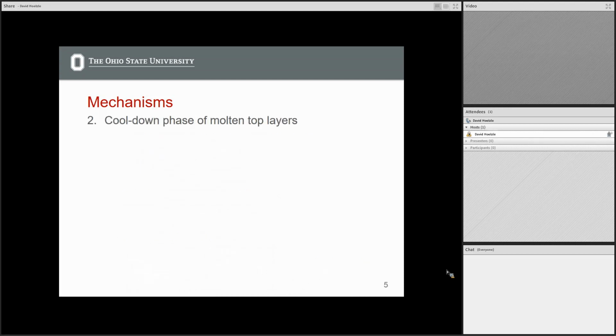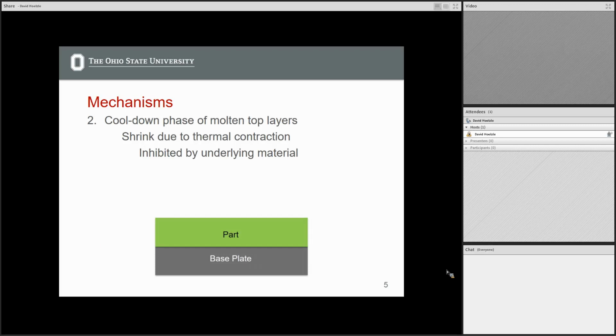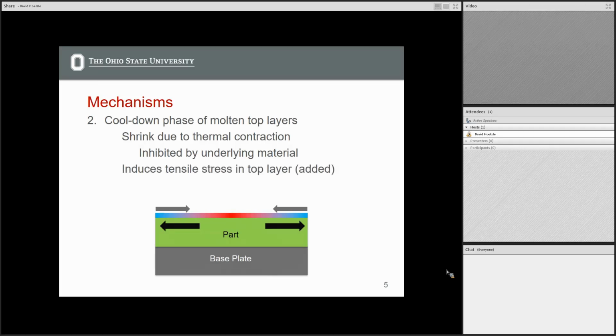However, the main one they wanted to focus on in their theoretical model was the cool down phase of the molten top layers. So what that ended up meaning was that the molten top layer wants to shrink due to thermal contraction. However, it's going to be inhibited by the underlying material that it's fused to that isn't molten. So, a visual to help explain this. If we have our base plate and our part that we've already built up here, we're going to add a molten top layer to this part. And as it begins to cool, it's going to want to thermally contract. However, because it's fused to that part below, it's going to be unable to do so. And this is going to induce a tensile stress in that top layer, while also applying a compressive stress to the layers below. Now this is going to be important to explain a figure a little later on.